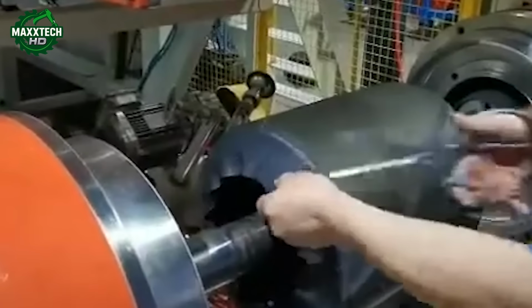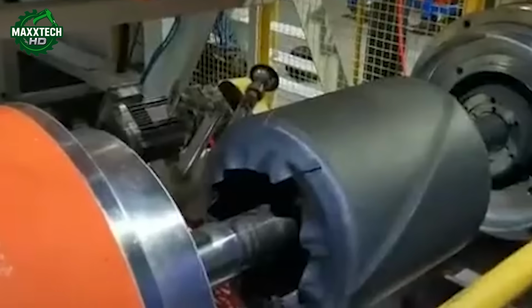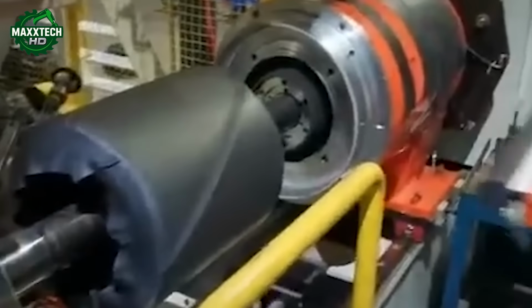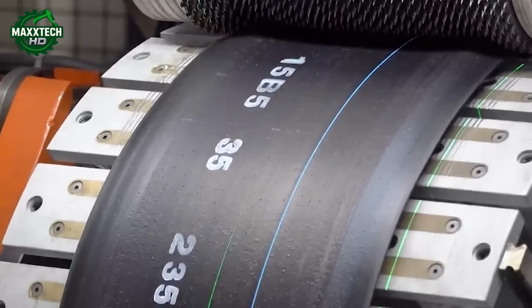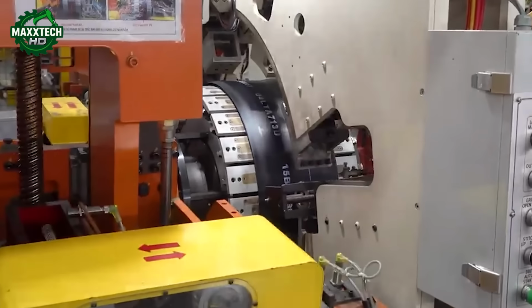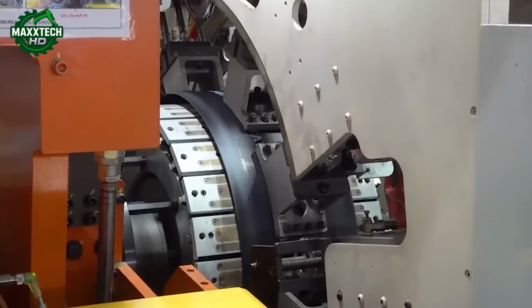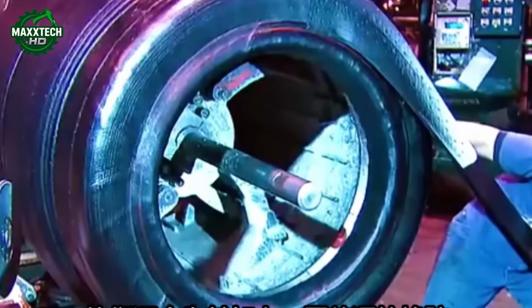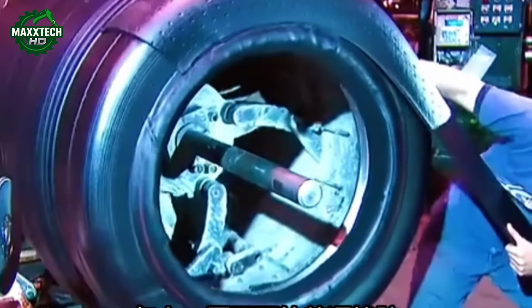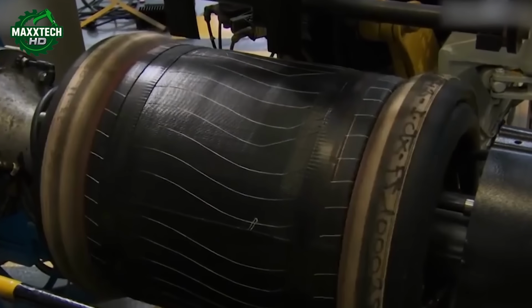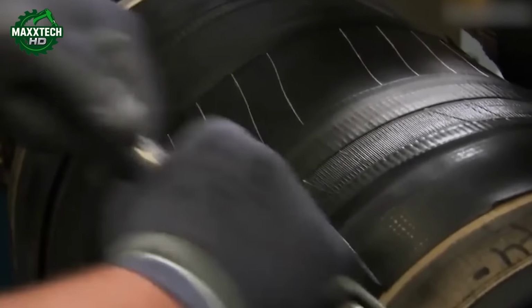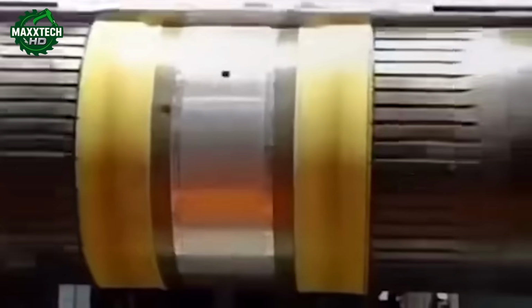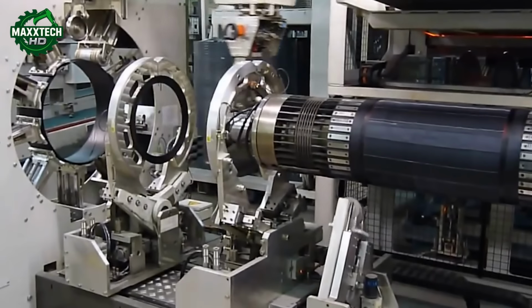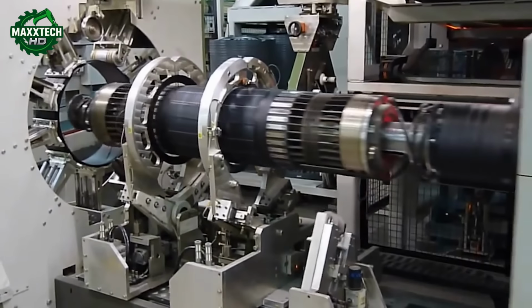Once the layers are ready, the tires are moved into top-secret molds, where pressure and heat force the rubber to adopt the deep tread pattern that makes them capable of gripping the soft, sticky sand of Alberta. This molding process takes 12 hours, during which the tire gradually cools and solidifies into its final shape. After molding, every tire undergoes a rigorous inspection. Technicians carefully check for blisters, poor molding, or other imperfections that could compromise performance. Only after passing these tests does a tire earn the green light for deployment.